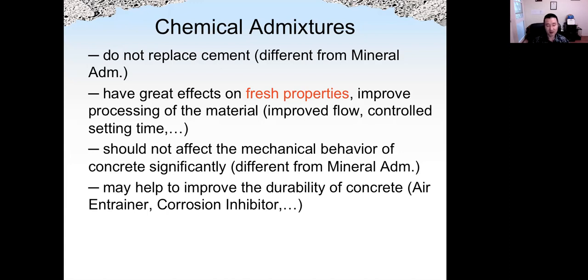Okay. But this should not affect the mechanical properties of concrete significantly. Right. So that means the strength of concrete should not be affected by chemical admixtures if the other mix proportions do not change. Okay, that is also different from mineral admixtures. Okay, so when we replace Portland cement with 10% of silica fume, the strength will go up quite a lot. Okay, but if we just add some chemical admixtures to the mix, the strength should not change too much. Okay, so chemical admixtures can improve the durability of concrete in the case of air entraining admixtures or corrosion inhibitors. Okay, so these are two types of chemical admixtures we will discuss.